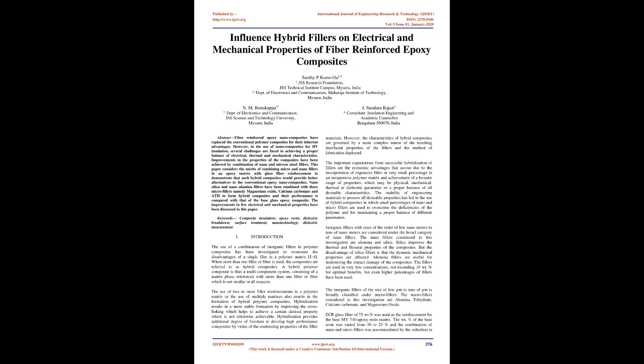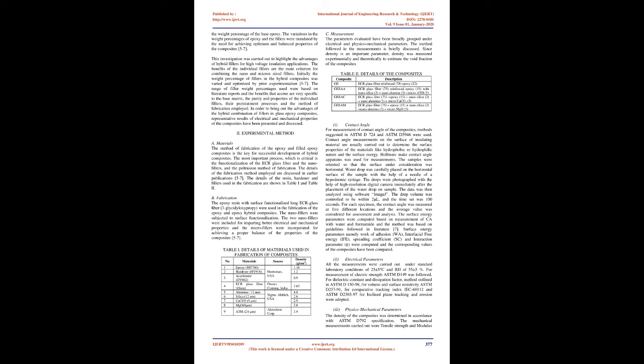Inorganic fillers with sizes of the order of few nanometers to tens of nanometers are considered under the broad category of nanofillers. The nanofillers considered in this investigation are alumina and silica. Silica improves the thermal and flexural properties of the composites. But the disadvantage of silica fillers is that the dynamic mechanical properties are affected. Alumina fillers are useful for minimizing the impact damage of the composites. The fillers are used in very low concentrations, not exceeding 10 weight % for optimal benefits, but even higher percentages of fillers have been used.